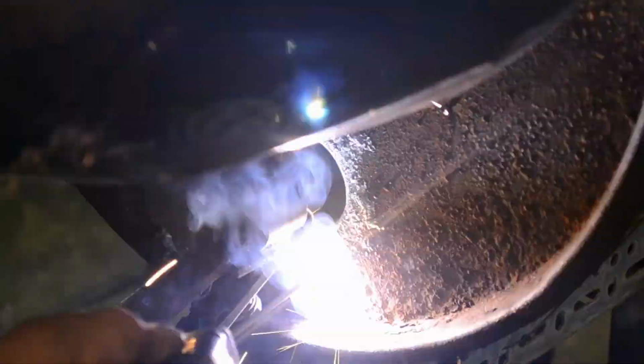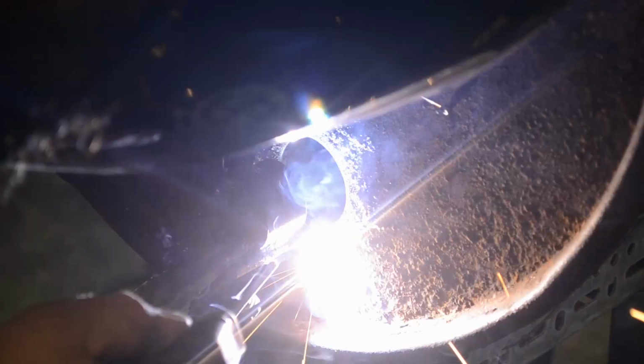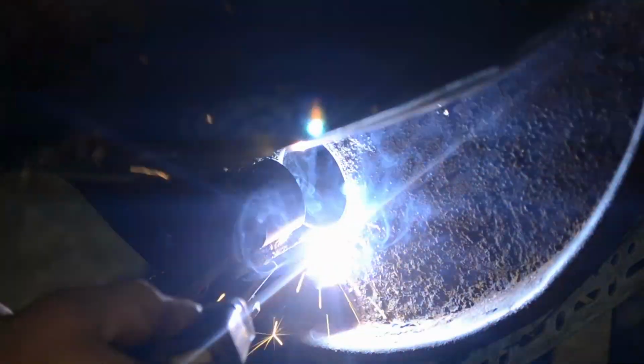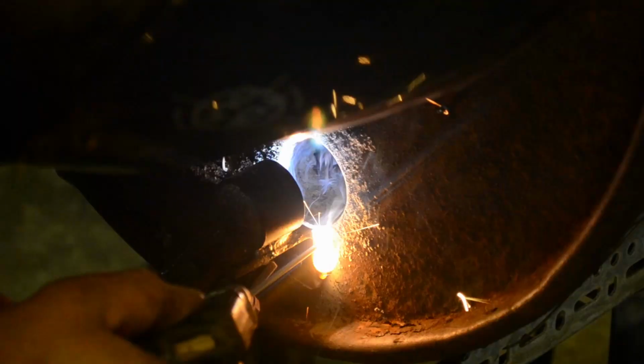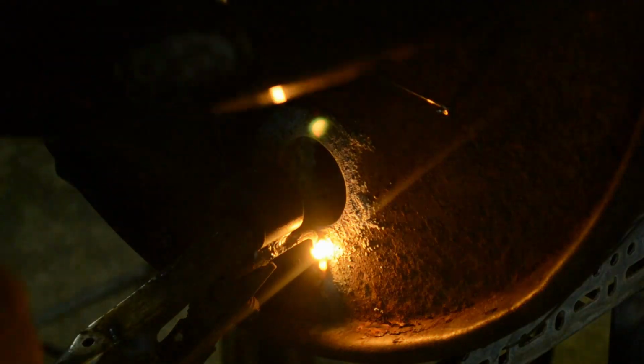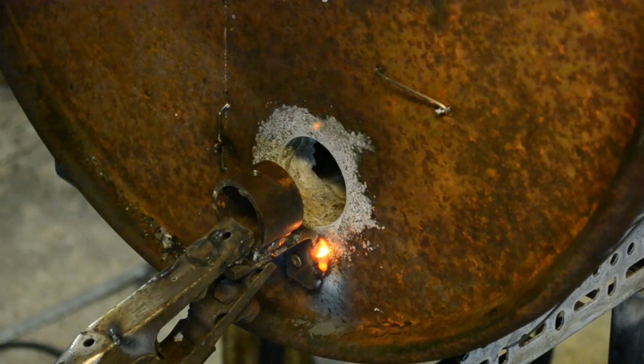And once I had it all rigidized, and once I had it all cured and had the burner set up properly, I could get it up to 820 degrees Celsius, which is around 1550 degrees Fahrenheit, within 20 minutes of first firing. So from cold, 20 minutes to get to heat, which is quite impressive.